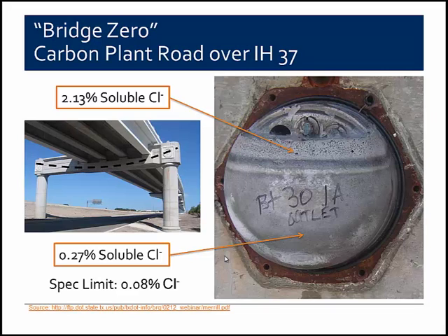And you can see the lower half, the grout below that dark band is very hard, very dense, very solid, but it did have a 0.27% soluble chloride content based on weight of grout, not weight of cement. The top portion above the black band, you can see is very porous. It's actually very soft. It's clay-like or gelatinous in texture. You can remove it with your finger. Notice the extremely high soluble chloride content in that material. That's 2.13% by weight of grout, which is many, many times the specification limit. The black band in that grout was actually determined to be unreacted silica fume, which was one of the constituents of the grout mix.